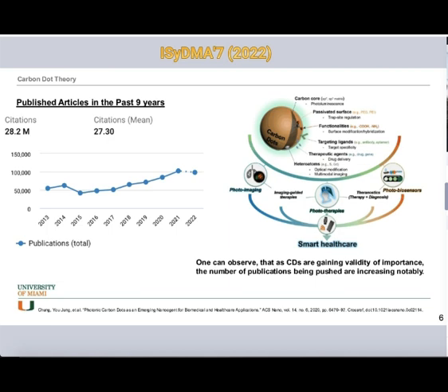So at the moment, at least in 2022, the main application is really related to therapeutic work, mainly in cancer research, because we can put a drug ligated to the carbon dots. Carbon dots are a very good nanocarrier. If you want carbon dots really soluble in water, you use polyethylene glycol for the passivated surface. If you want electropositively charged carbon dots, you use the polymer PEI. So as I just mentioned, we have quite a lot of different possibilities.